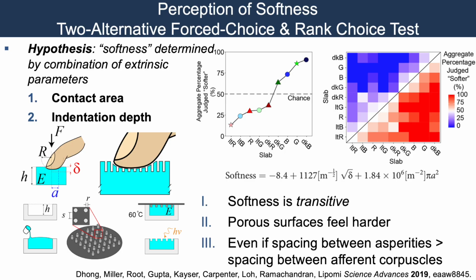And the way that we did this experiment was the way that you do an optometry experiment. So softer 1, softer 2, softer 3, softer 4, and so on. And we did close to 90 paired comparisons per participant. The other way to plot the data is to plot the results of the head-to-head comparison.